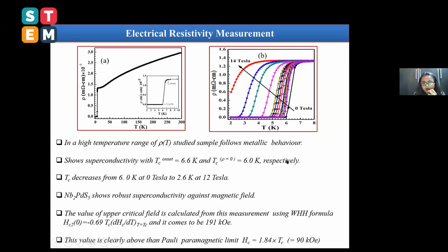After structural characterization, we performed the electrical resistivity measurement to check whether it is a superconductor or not. So we measured electrical resistivity, rho versus temperature, and in a high field you can see that this sample shows metallic behavior, while this is the zoom part of this curve. Here you can see that it shows superconductivity with onset 6.6 Kelvin, while the TC at rho equal to 0 is 6 Kelvin in this case.